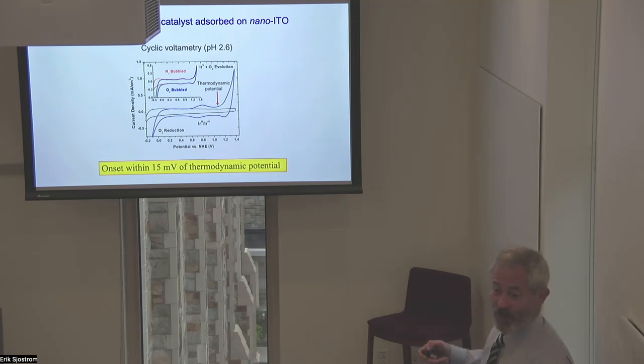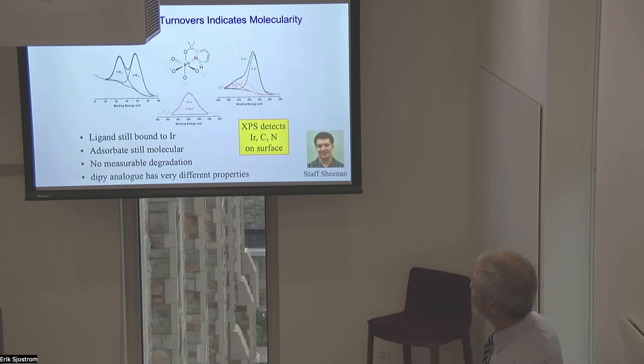This is really amazing. Normally, when you have a water oxidation catalyst, you have to go to a much higher potential. This is referred to as the overvoltage in a reaction, typically hundreds or maybe even 500 millivolts. So this is really the onset almost at the thermodynamic potential, very low overvoltage, and it's incredibly stable. So this is some work also from Staff.